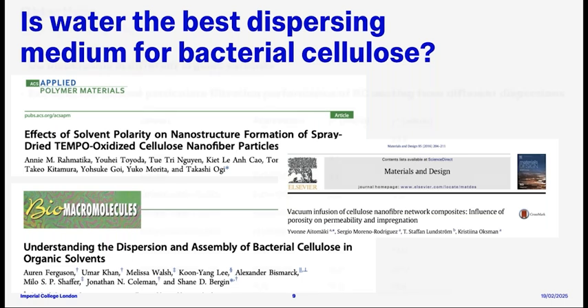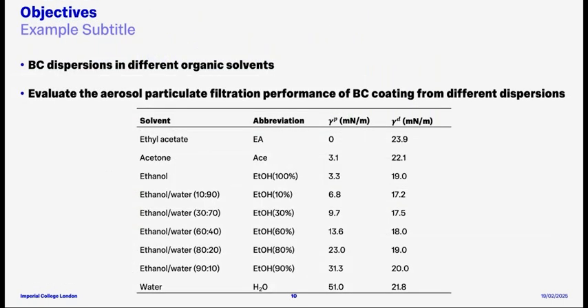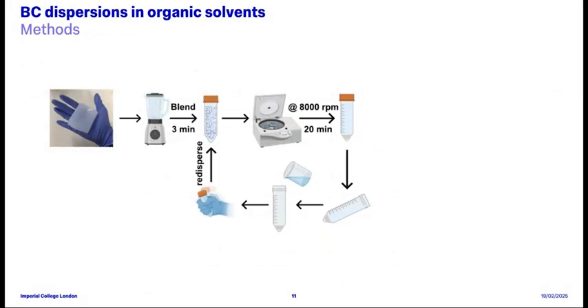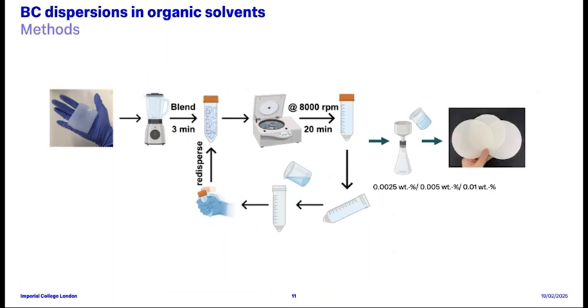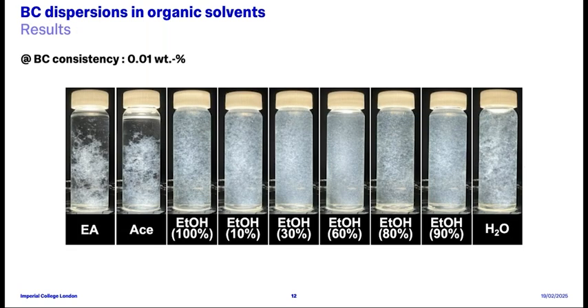And to study this, here we have dispersed bacterial cellulose in various selected solvents by solvent exchange, namely ethyl acetate, acetone, and a series of ethanol-water mixtures of different volume ratios. And similar to our previous experiments, the bacterial cellulose suspensions from different solvents are then vacuum filtered onto a woven fabric substrate at 3 different grammages and oven dried. And first, by inspecting the visual appearance of the dispersion containing bacterial cellulose, it can already be observed that the dispersion quality of the bacterial cellulose in various organic solvents is indeed different.